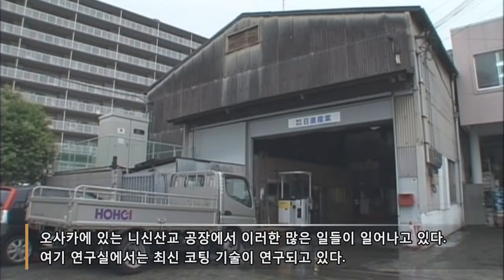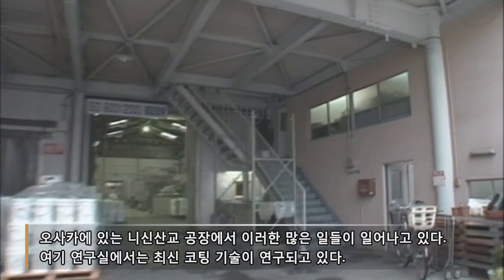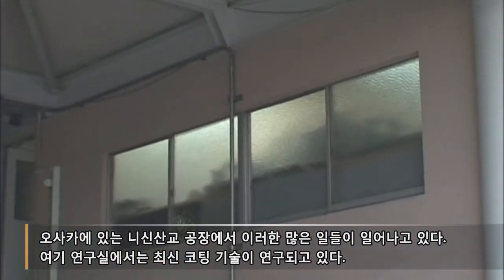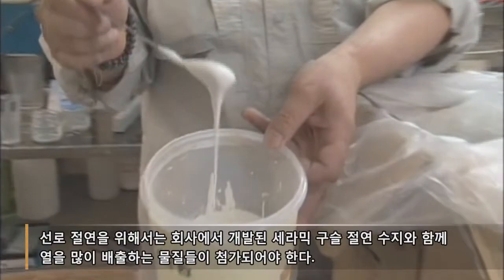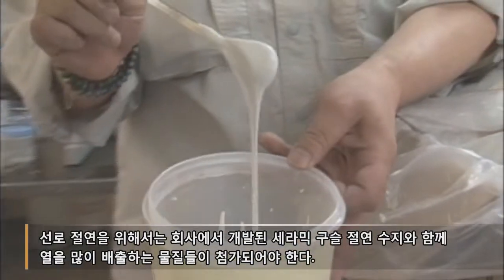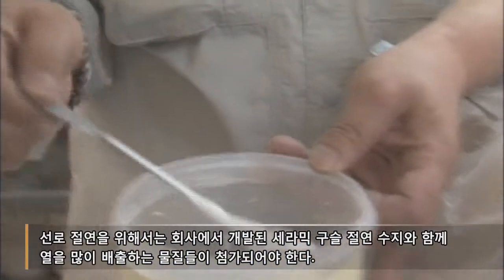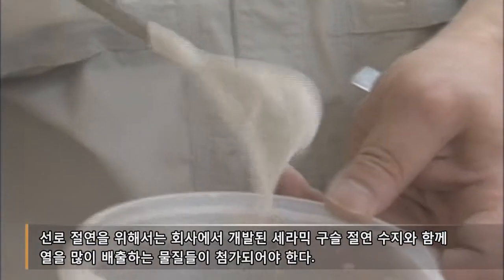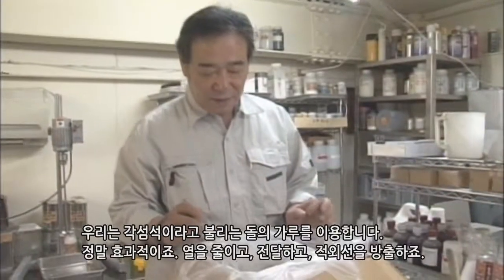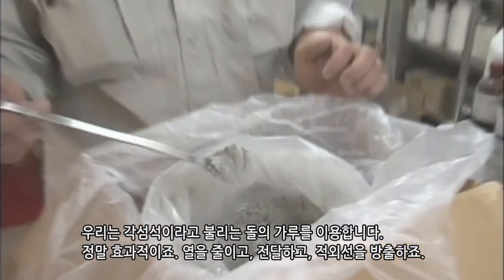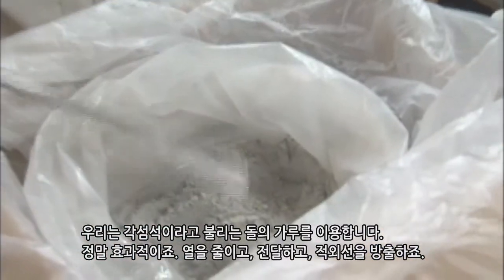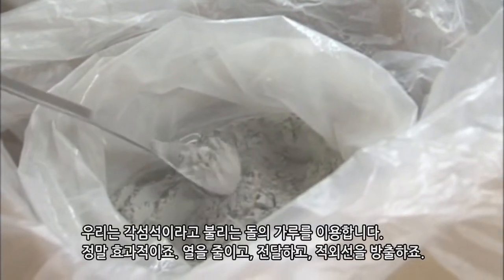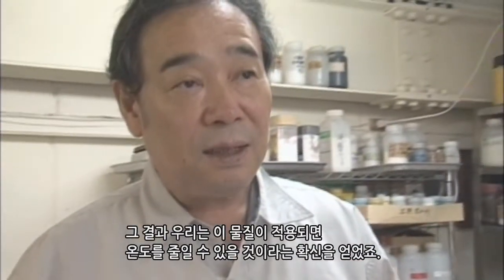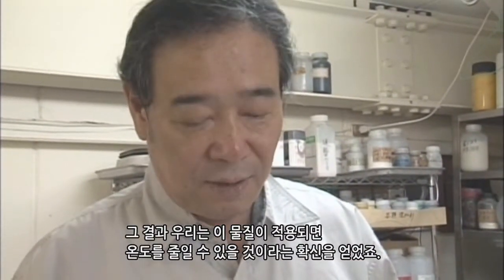Much of the work is done at Nissin Sangyo's Osaka factory. This lab is the front line of coating development. For rail coating, a material of high heat emission is added, along with the ceramic beads that are used in the company's other insulating resin. We use powder from a stone called amphibole. This works really well in reducing heat and changing heat to far infrared rays. As a result, we can expect that it will decrease a structure's temperature when it's applied.